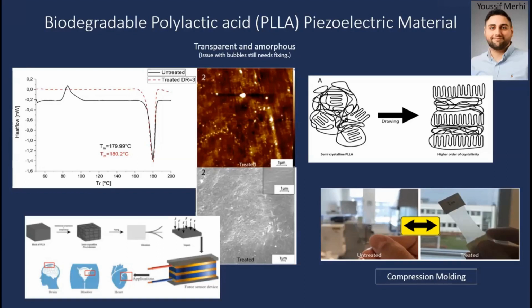But this electric field is really, really high. And sometimes it's not really possible to put every material that you are printing and every device that you are printing into the poling environment. So we wanted to look at a material which did not require any poling. And then we did our own study, and we found that there is a naturally occurring PLLA material, which has a very, very weak piezoelectric signal. It's very weak. But the idea was to pick this up because it's completely biodegradable. It does not require any poling, and then transform it and try to enhance its piezoelectric properties. And this is exactly what we are doing right now.